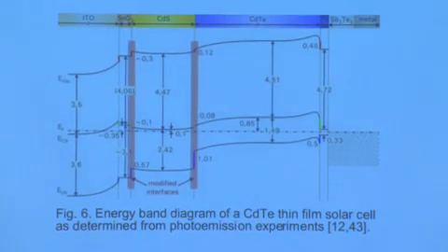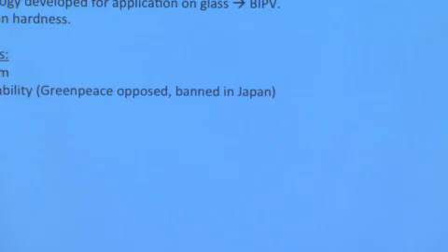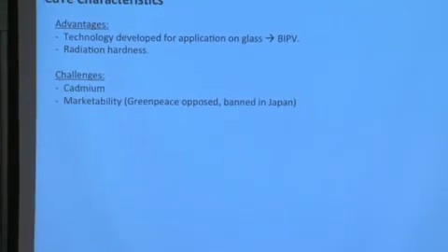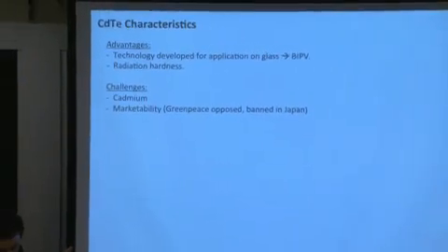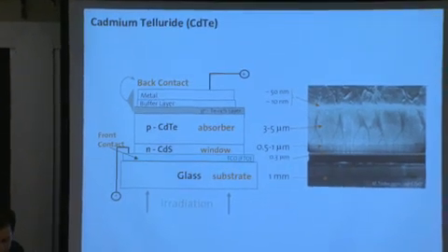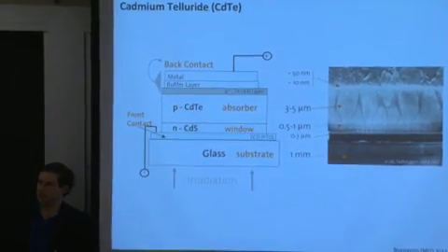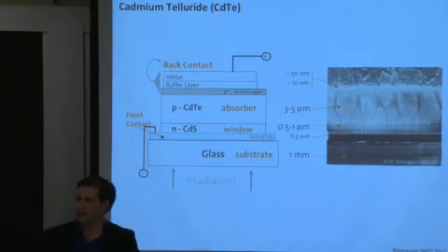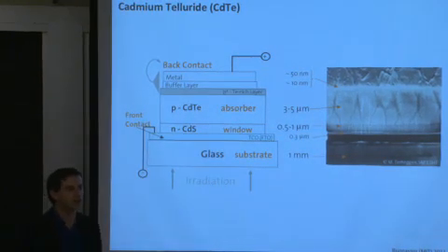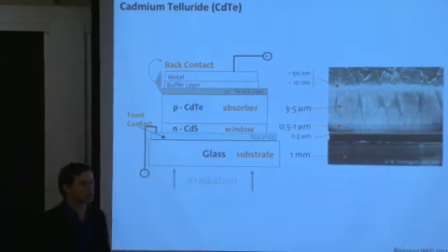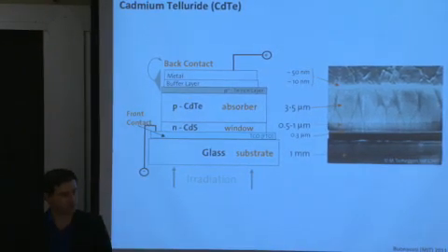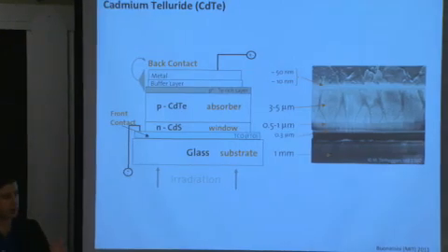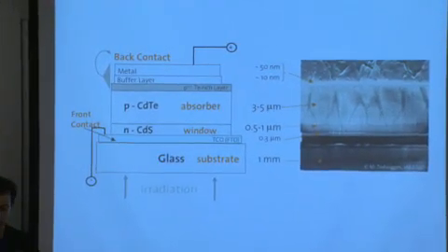And the characteristics, it's very well, the deposition technology of CdTe, as I said, it's nature's gift to humankind. If you put cadmium and tellurium together in a pot and start heating it up, what evaporates is CdTe. It congruently evaporates. So you could use a process called closed space sublimation, where you essentially sublime your CdTe and you deposit it onto your substrate.